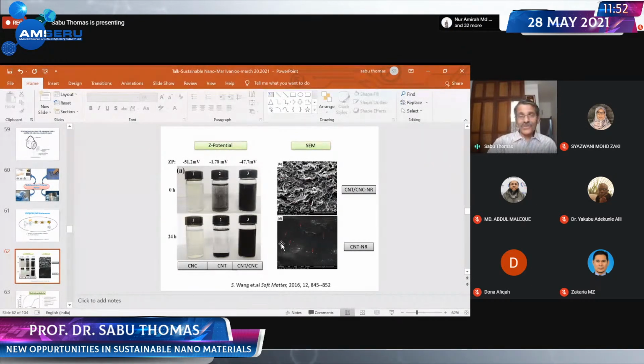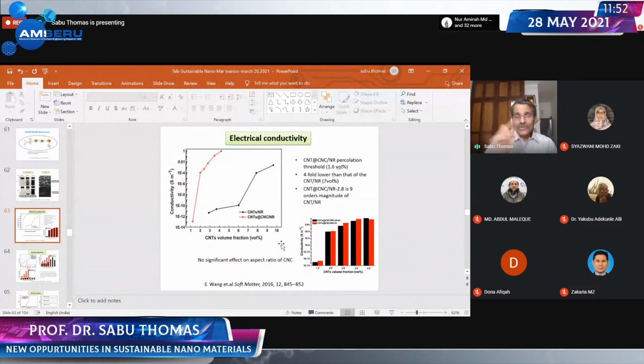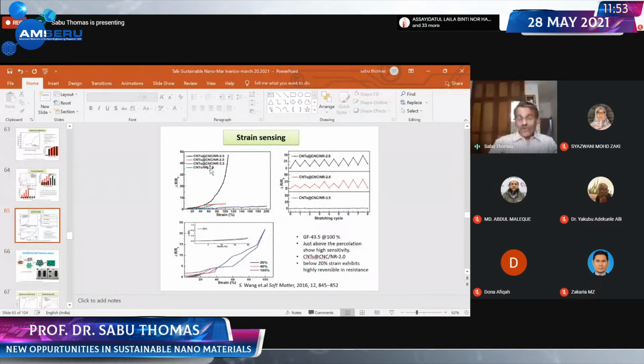Now I'm going to show you the most interesting observation. If you put carbon nanotube into natural rubber, of course you get a percolation. After 6 volume percent of CNT, this is the percolation region. This is conductivity as a function of CNT volume fraction, with natural rubber and CNT together. But if you combine CNT and nanocrystals together, look, the percolation is shifted to a lower concentration of CNT. You get a percolated structure at 1.5 concentration of CNT. And this combination has excellent mechanics, good modulus, good strength, and at the same time is highly conductive. And this is a beautiful material for sensing.